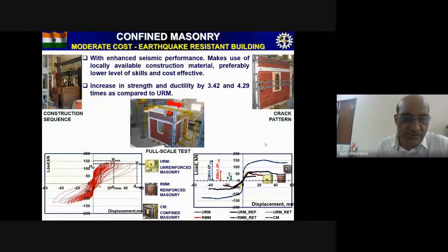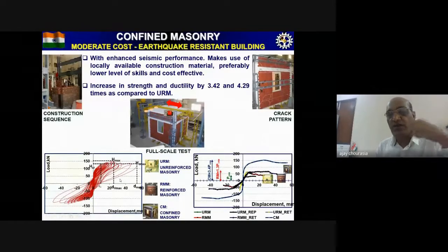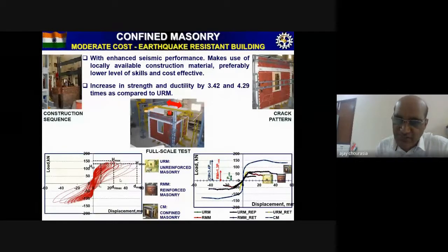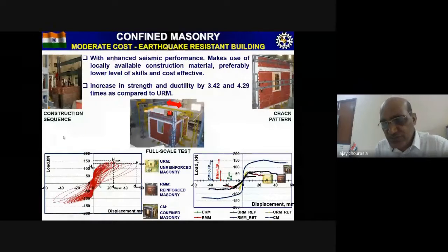During the testing, this is the hysteretic loop which was created, and which clearly shows the area under it. This hysteresis curve shows the energy dissipation capacity of the test structure. To understand it in a better fashion, a load displacement curve was plotted, which clearly shows the maximum load attained by this building was 152 kN, with deformability of around 64 mm.